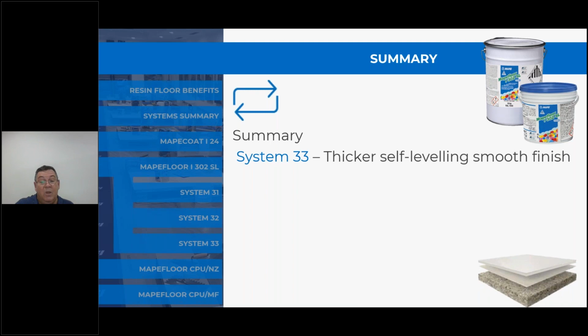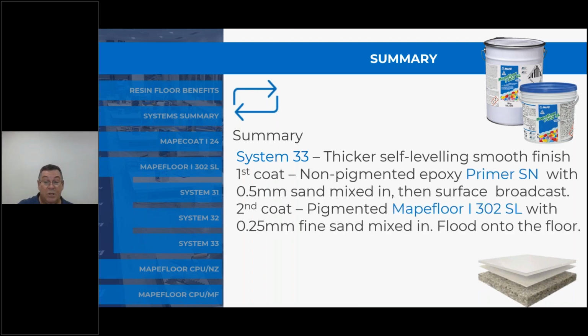System 33, it's the thick self-leveling smooth finish. First coat is non-pigmented primer SN. The second coat is the I-302 with the 0.5 fine filling sand installed into the mix, and it's flooded onto the floor, troweled out and spike rolled to a smooth finish.